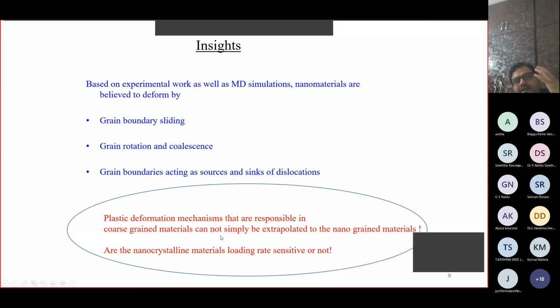So the take-home message from whatever I presented till now is that plastic deformation mechanisms that are responsible in coarse grain materials, where the average grain size is more than 100 nanometers, cannot be extrapolated to the materials where the average grain size is less than 100 nanometers. Because the plastic deformation events are totally governed by different sets of lattice defects in these two regimes. So therefore, the knowledge that we have at higher grain size cannot be extrapolated down to the nano regime, or in other words, whatever you see in nanometers cannot be extrapolated to the conventional materials.